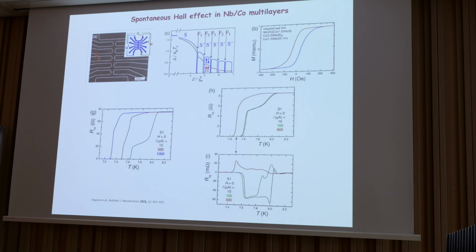Now, what is interesting is, where is the TC? Where is the onset of anything? If you look at the red curve here, I would say the onset of the Hall effect is maybe somewhere here. We look at the resistive transition, nothing. So it's deep inside the resistive state, a very flat dependence. Now if you look further, the onset of resistance here occurs somewhere in the middle of the Hall effect. So this is already deep inside the flux flow state. Note that all this region is a flux flow state.